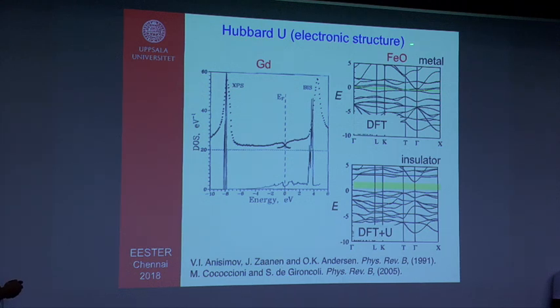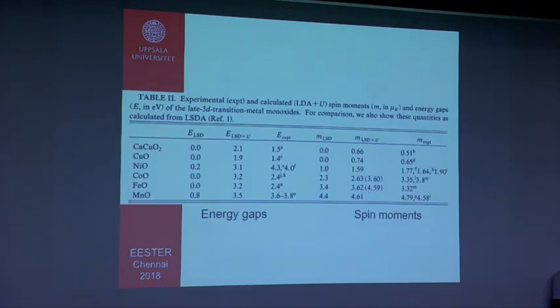If you look into iron oxide, which is a transition metal oxide, and do an LDA calculation, a DFT calculation, you get a metallic solution. You see that this is the Fermi level, the bands are crossing the Fermi level. If you do DFT plus U, a correction on the iron d orbitals, you open up the states, and there is a gap opening up which gives you the correct solution. So in some of the cases, we see that DFT plus U actually works pretty okay.